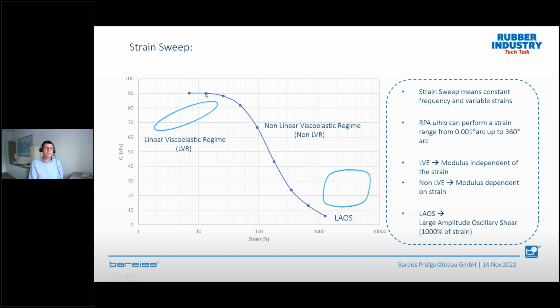If you remember, we said we calculate G prime as the torque divided by the strain multiplied by the die factor. So if we double the strain, and at the same time double the torque, the modulus is the same. So we are in the linear viscoelastic regime, which gives you very nice Lissajous figures. That is what you see here. If you increase the strain, we go to the non-linear viscoelastic regime.